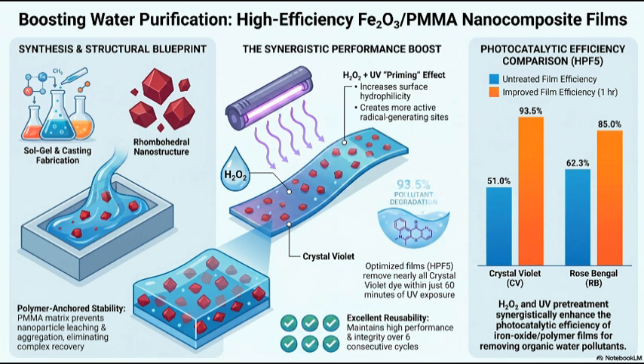Now that the floodgates are open, we can look at the actual performance data to see this microscopic battle play out. The researchers tested several different compositions, but the champion composite was designated HPF5. Right. HPF5 featured an optimal loading of 3.32 weight% of the Fe2O3 nanoparticles within the PMMA. They submerged pieces of this specific film in a 5 milligram per liter solution of the toxic dyes and turned on the UV lights. The contrast between the untreated locked vault and the treated open vault is staggering.